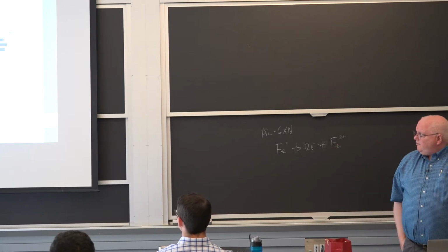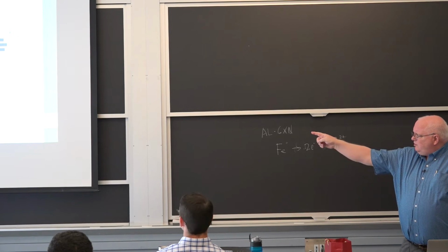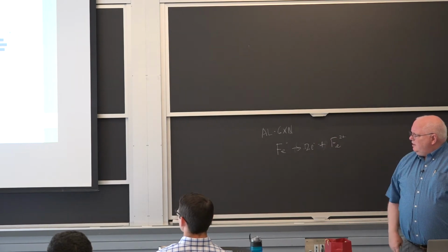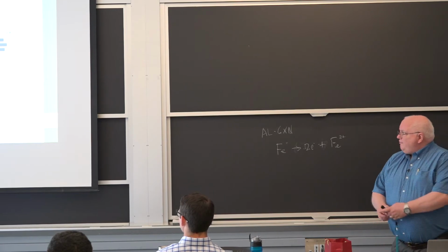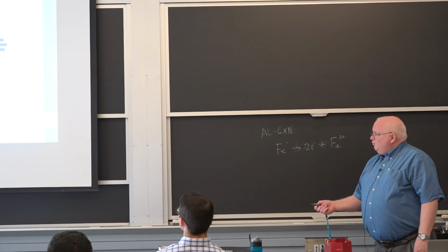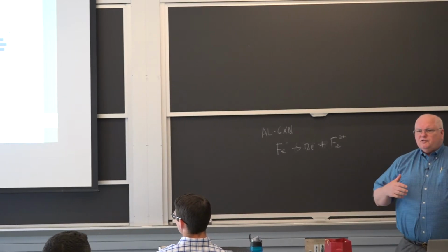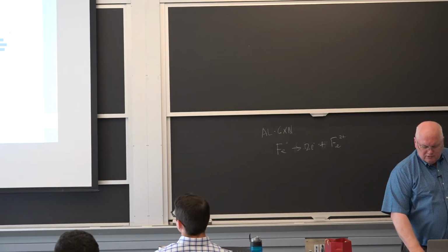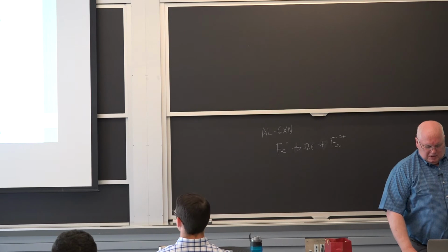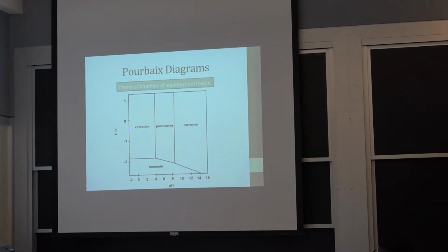Anyway, so there is this galvanic series, and things can change. You see pure aluminum and aluminum alloys on here are in different locations, different potentials. You get a half a volt here between aluminum and aluminum alloy. Not enough to drive corrosion by itself. You just have something else and get yourself up to about 0.7 volts or 0.8 volts, and you'll get your corrosion.